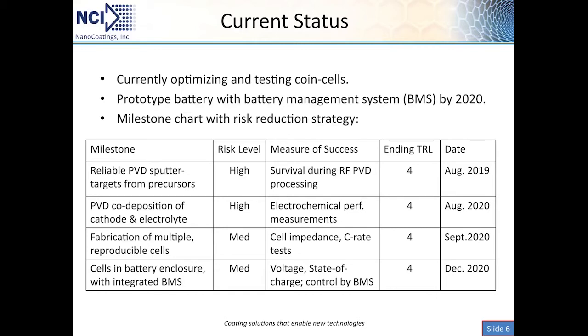during RF-PVD processing. We also have been performing PVD co-deposition of cathode and electrolyte materials instead of just layer by layer. The purpose here is to increase the amount of active material in the co-deposited layer. Performance has been measured by electrochemical means by the School of Mines. We're also fabricating multiple reproducible cells now using larger area substrates, for example, 3-inch by 6-inch, from which we can get 10 to 12 coin cells per deposition run.